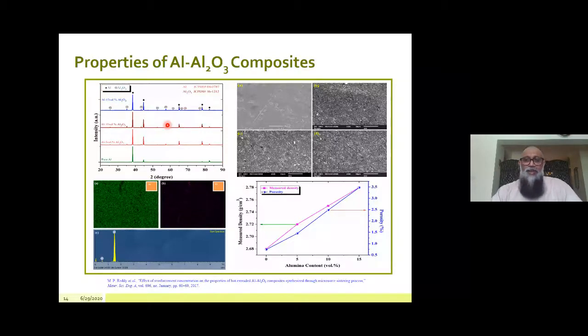Okay. Let me quickly go through. These are the XRD spectra of various compositions, and these are the SEM images which show the distribution of aluminum oxide particles in the matrix, and we can see the density and porosity increase with the increasing content.